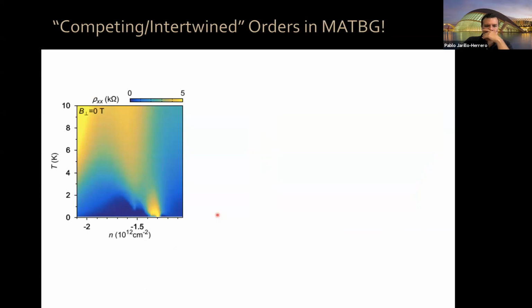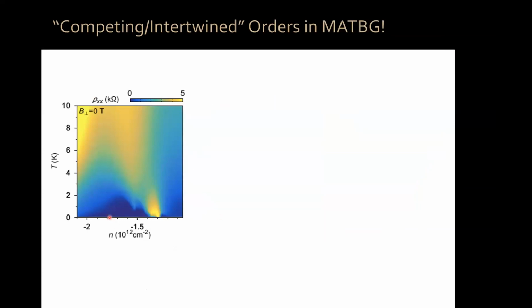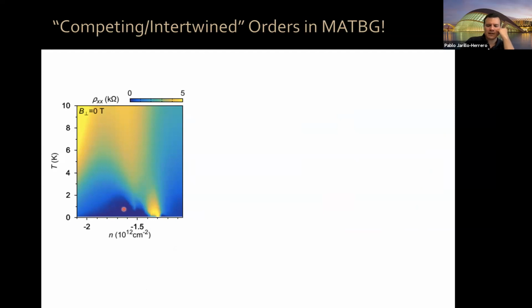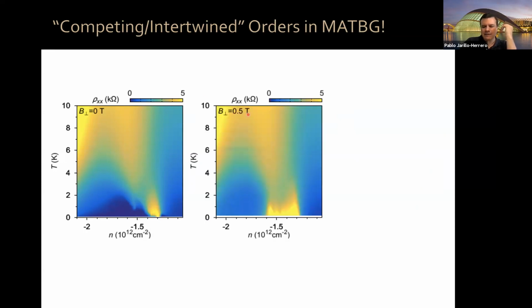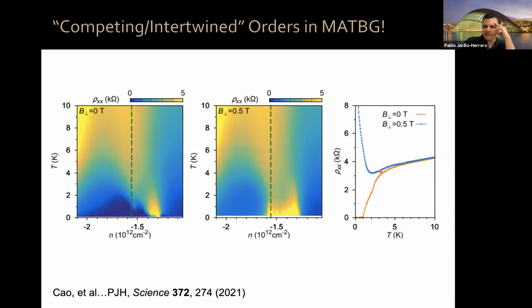One of the things that we did is we saw, okay, let's see what is really happening. This is at 0 magnetic field so that we can see the superconductivity. What happens if we apply a small perpendicular magnetic field so that we kill superconductivity, and we can see what is really trying to develop underneath here? So we measure this data now at a small perpendicular magnetic field, half a Tesla, and then we can see that this resistance ridge becomes an insulating state at low temperature. In fact, if you measure at this density, where we had the depletion in Tc, we see that at 0 magnetic field, you have a superconducting state. At finite magnetic field, you have an insulating state at that precise density.